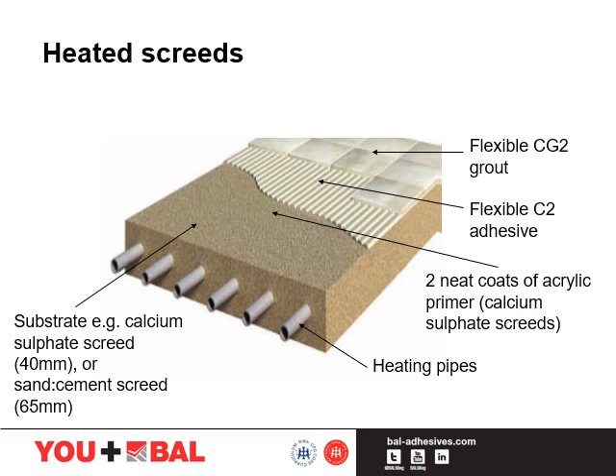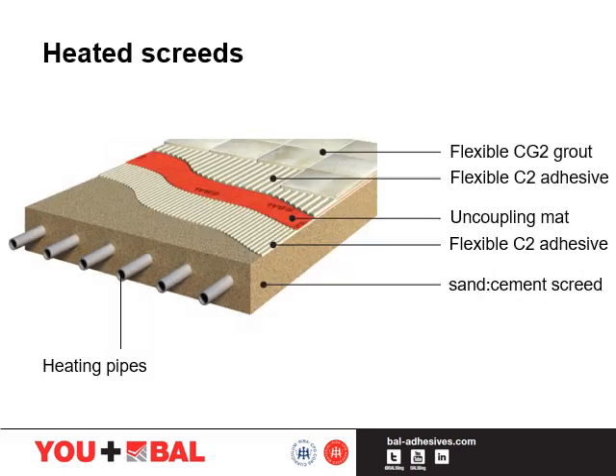This and the next slide show the basic build-up of two types of heated floor. This is a typical underfloor heating system on a screed with a tiling installation above. The specification in terms of adhesives and grouts calls for a minimum C2 tile adhesive with a minimum CG2 grout. Highly polymer modified products, especially ones with rubber crumb technology, offer a brilliant flexibility and deformability to accommodate considerable movement and vibration. In this image, we show the use of an uncoupling mat. This could have been incorporated due to the size or type of tile used.